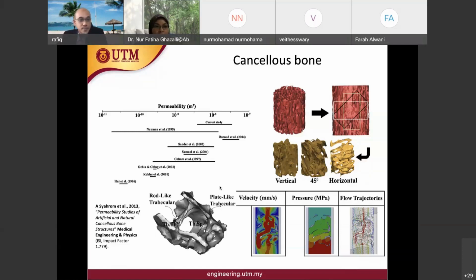So there you go. This is a permeability study, fluid flow mechanics, fluid flow dynamics. You can see that we can obtain results for the velocity, pressure, and flow trajectories inside the cancellous bone. And that bone is about this size, very small. But we can develop the 3D model using micro CT scan and then analyze the fluid flow and flow trajectories. And we compare, of course, with other published results as well.